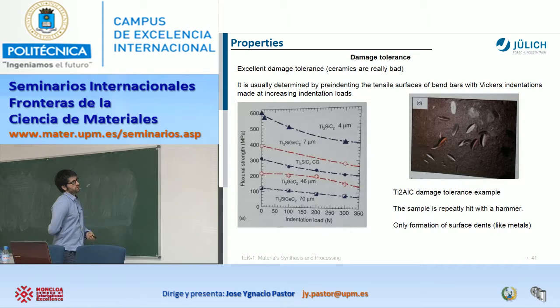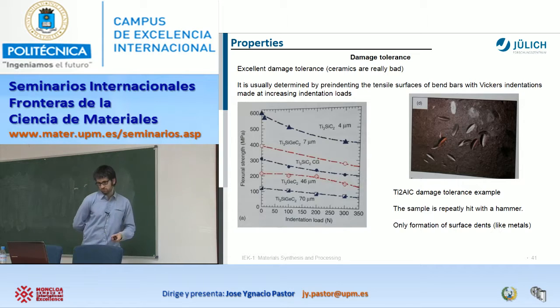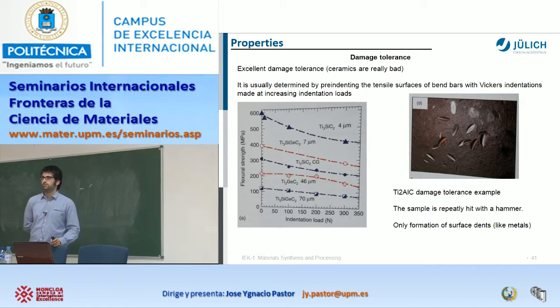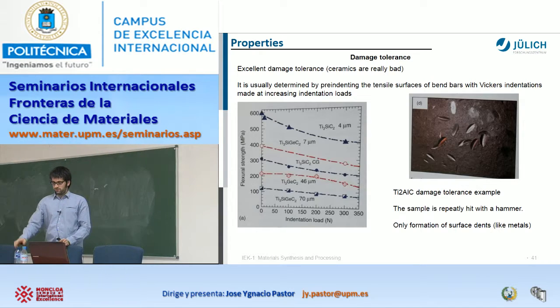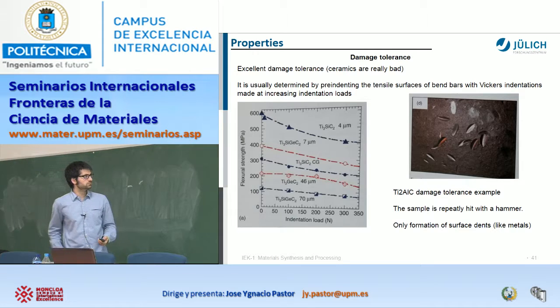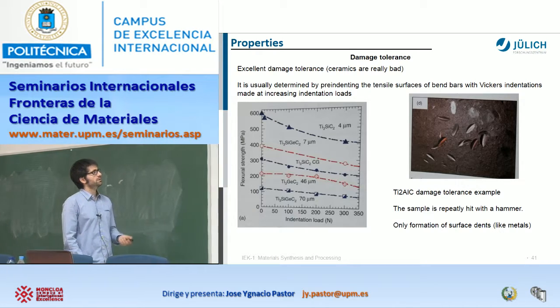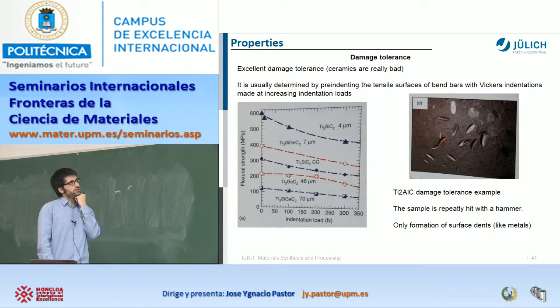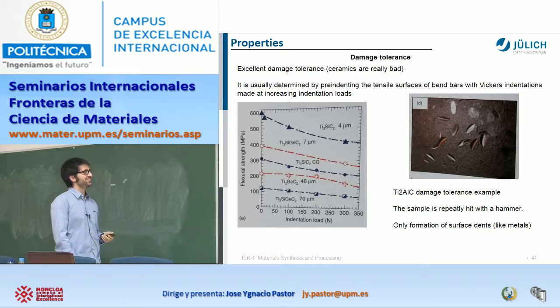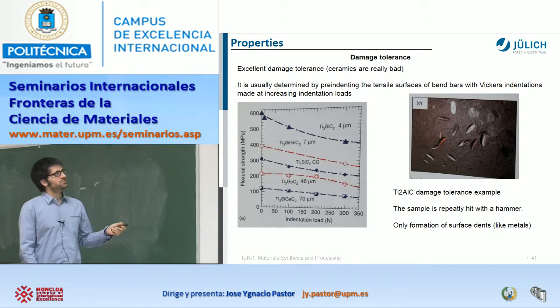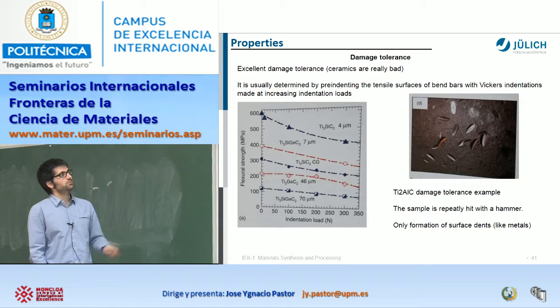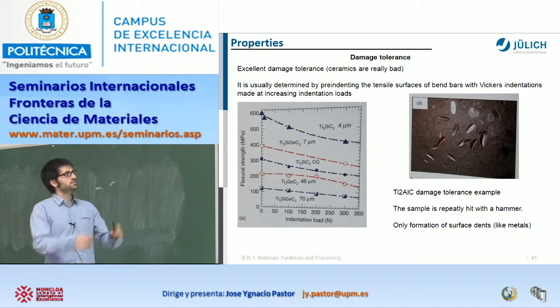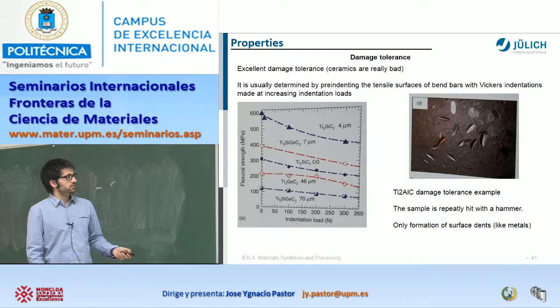Another important thing in ceramics is always the damage tolerance. This is also the problem of the ceramics. If you have a ceramic and it falls down, it breaks, but in MAX phases some of them are not like that, okay? To measure the damage tolerance, normally what you do is some indentation and measure the tensile response of your material, and when it breaks. But here, as you see, they can perfectly keep, or well, maybe this one not so much, but they are totally constant in the flexural strength with the number of indentations.